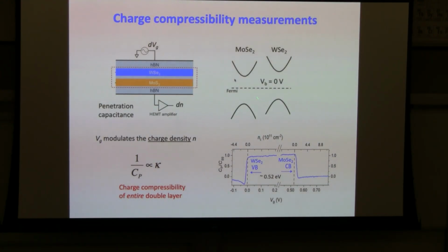But once you move the Fermi energy here, so that it touches the conduction band minimum by your gate, you can see that there's suddenly a drop in the penetration capacitance, because the system now becomes metallic and the metal will just screen out the penetration field, and you collect nearly no charge from the bottom gate. So that's the conduction band edge. This drop is the conduction band edge of the moly. And equally, you can move the Fermi energy to the valence band maximum and that produces another drop, and that would be the valence band edge of the tungsten layer in this case.